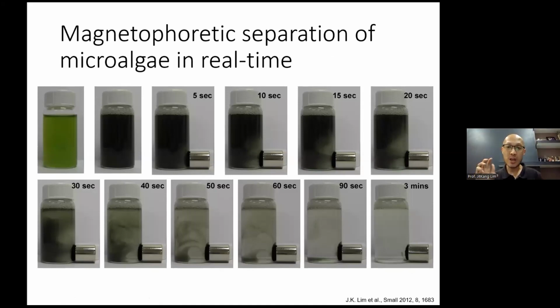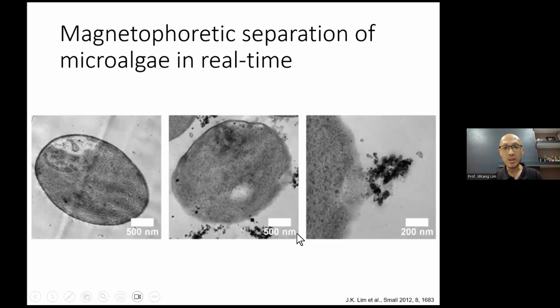So once we manage to attach the particles onto the cell, right, and we introduce a magnetic field, then we could see the microalgae after being mixed with particles, and we can manage to separate them out quite rapidly. And eventually, the water will turn crystal clear. In fact, we managed to separate most of the microalgae out from the solution. And if we look at the transmission electron microscope images of the particles, we could see the successful attachment of particles onto the cell.